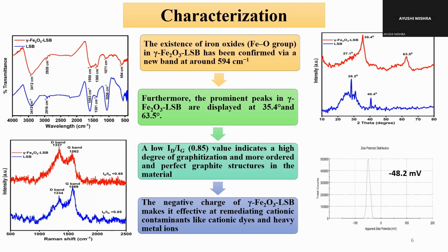In the XRD spectra, we can see a peak at 29° 2 theta, which is for the graphitic phase, and we have some additional peaks on the magnetic biochar at 35 and 63.5. That also shows the magnetic nature of the biochar.